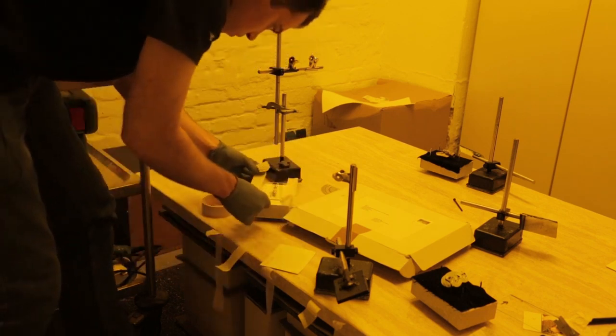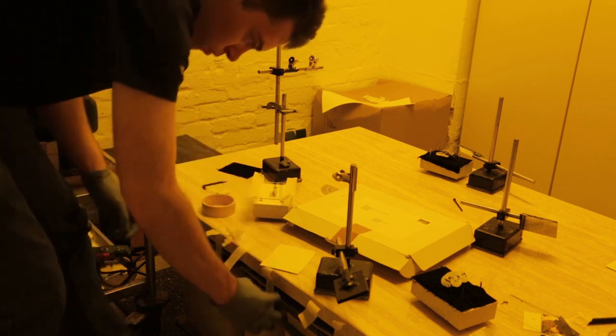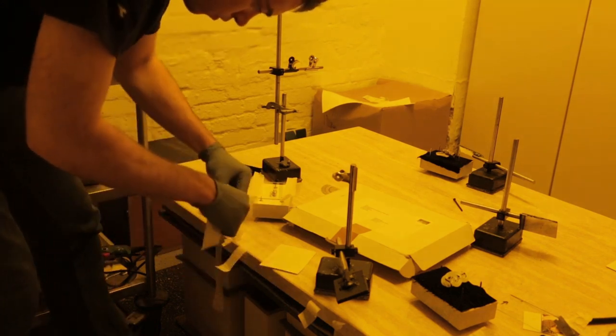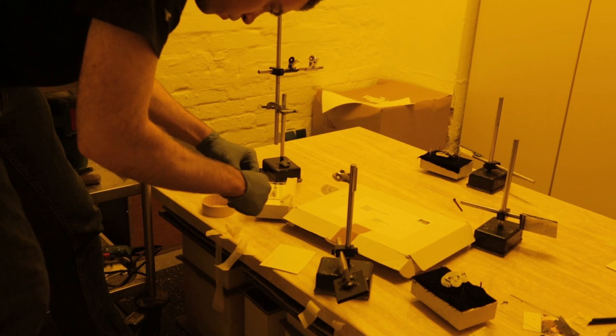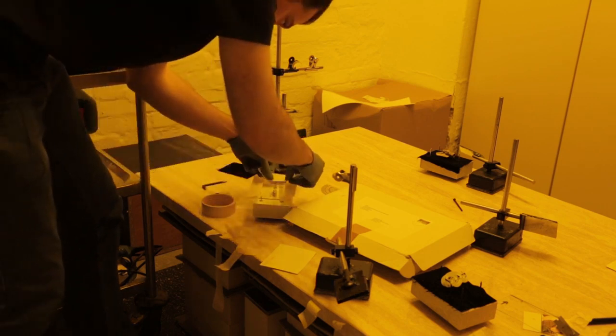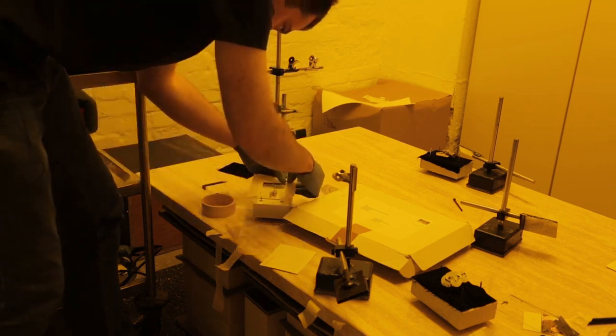Next, I put masking tape around it on the upper side of the plate. This is done to avoid internal reflections. The emulsion won't be exposed where the tape is covering it. After the exposure, the tape is removed and one can see the difference between the taped off unexposed areas and the exposed film. The exposed gelatin will be slightly tanned. Depending on the length of the exposure, this tanning will be stronger or lighter.